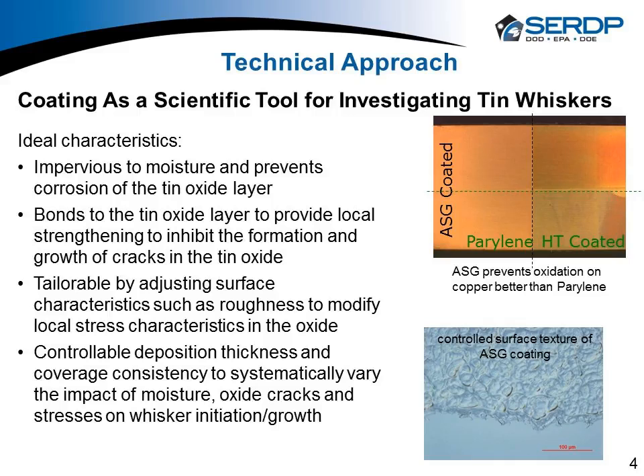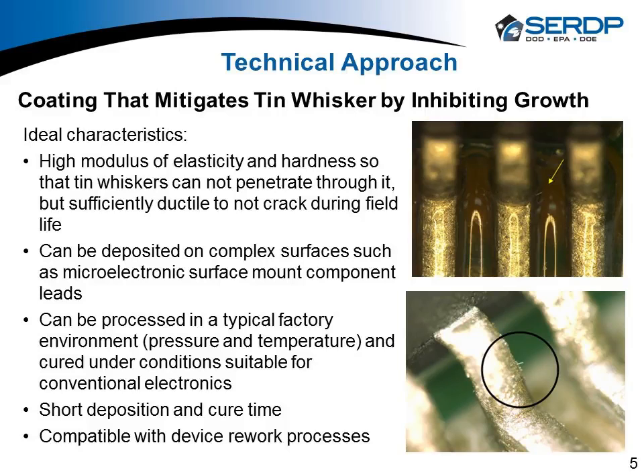You'd like the coating to be tailorable. So do I want it rough? Do I want it smooth? Do I want it to have less stress, lower, higher stress? What can you change in the coating that could then impact whiskers? And of course, I want to be able to deal with the coating in terms of its deposition thickness and its coverage. If it's a great coating, but I can't get it down in a repeatable, consistent thickness, I'm in trouble. Or if I have trouble getting it to have good coating coverage consistency, then it's not the most ideal thing to work with. If we go to slide 5, put my engineer's hat on.